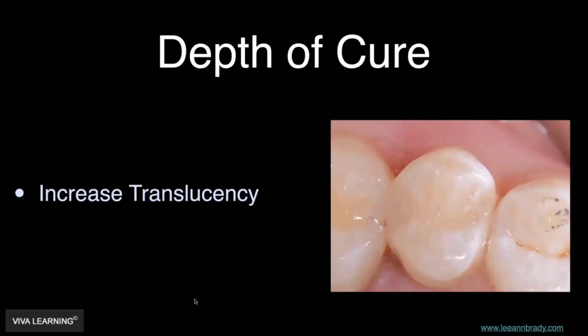The other thing they had to figure out is how are we going to get light all the way through a 4 to 6 millimeter bolus of composite? They did that in two ways. One, they increased the translucency of the composite. So across the board, most bulk fill composites tend to look more translucent. They don't quite have the same aesthetic opacity and light reflection as regular composites. And then the other way they did that is that they actually changed out some of the photo initiators. So they make the photo initiators more powerful. They don't put quite as many things in that retard photo initiation so that you can get greater depth of cure.